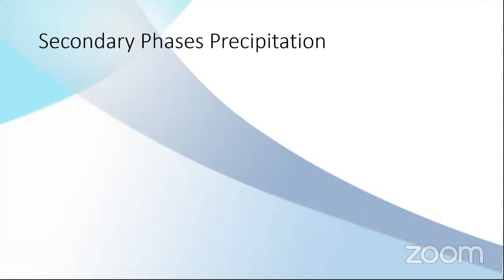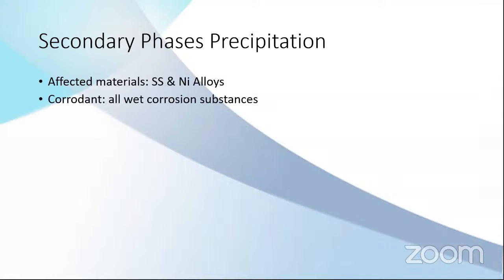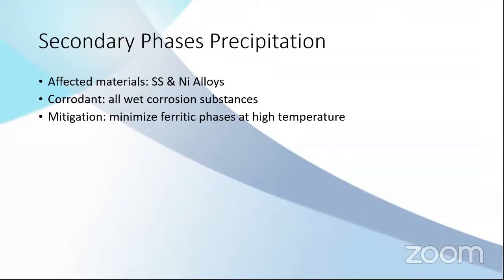And the third one is secondary phase precipitation. This is also mostly caused by weldments, affected materials, stainless steel, and nickel alloys. The same. All corrosive products can happen when you have this secondary phase. The mitigation is to minimize ferritic phase at high temperature. Ferritic phase is very susceptible. It's very easy to generate secondary phase.